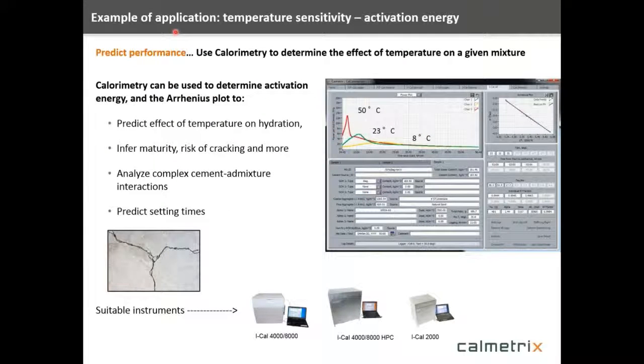Okay, let's turn our attention now to another benefit of the isothermal device, and that's the ability to change the temperature. As you remember, we can actually control the temperature around the environment, and we can use the fact that we can control temperature in order to look at the reaction kinetics. Where this might come into play is, for instance, if you want to calculate what's called activation energy. Activation energy is basically a tool that's used to look at the kinetics of the reaction. So we can take the calorimeter and run at least three different experiments at three different temperatures, and you can graphically see here the effect of the temperature on the reaction kinetics. And then we can take that data and calculate what's called the activation energy.